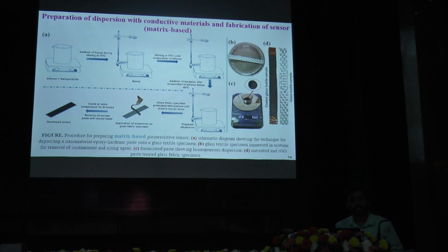This particular coating-based method is our patented method. Ethanol is initially mixed with the nanoparticles, that is reduced graphene oxide, and then epoxy is added into this mixture. You continuously stir this mixture at 75 degrees centigrade, then evaporate the ethanol and add the curing agent into the epoxy resin, then apply it onto the substrate, that is glass textile - this is how we develop this sensor.